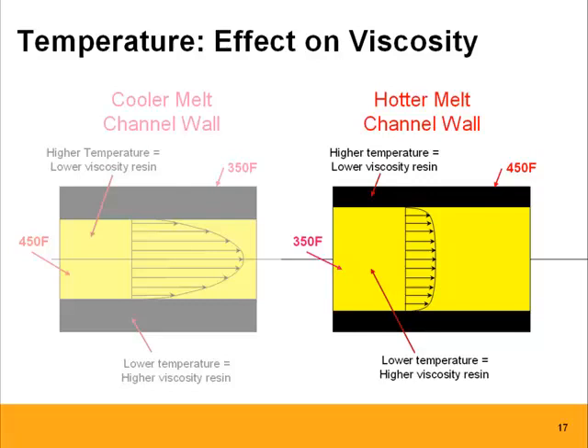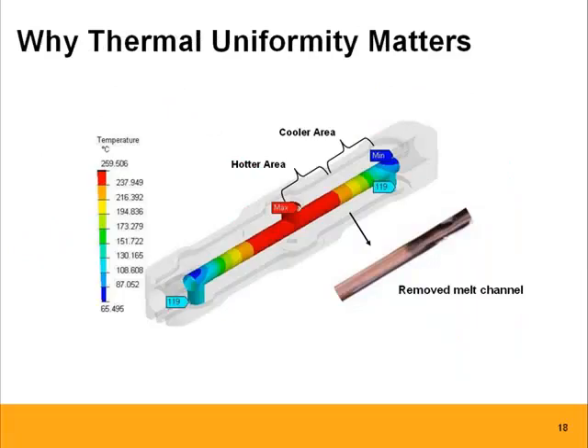So let me move on to thermal uniformity and why that actually matters, and it's of course closely related to the temperatures. This would be a manifold that wouldn't necessarily be optimized. It has a very hot area right around the entrance of the resin, and then a cooler area on the other side. What we actually pulled from this manifold is also the plug, and you can see already a little bit, I have a detail in a second, this is lighter. That means if we change color from black to white, we can see the white already coming through in the hotter area, versus there's more black on this side.